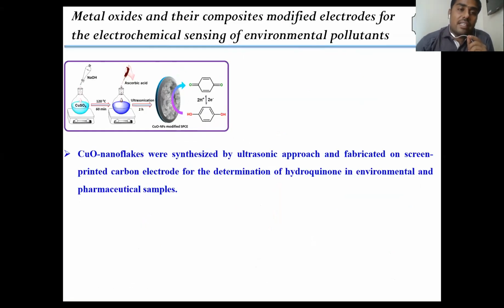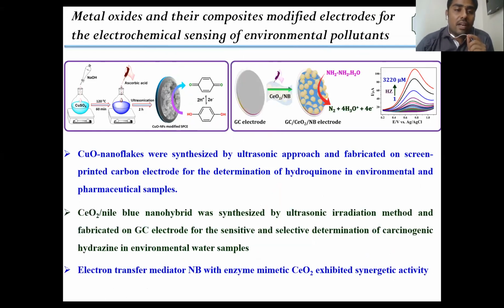So we also utilize the metal oxide nanoparticles and their composites: the copper oxide nanoparticles for determination of hydroquinone, and cerium oxide nanoparticles with the Nile blue. Nile blue is an electron transfer mediator, the organic linker. It is an electron transfer mediator with an enzyme mimetic CeO2 that exhibited synergistic activity, and we utilize the CeO2 Nile blue composite for the determination of hydrazine.